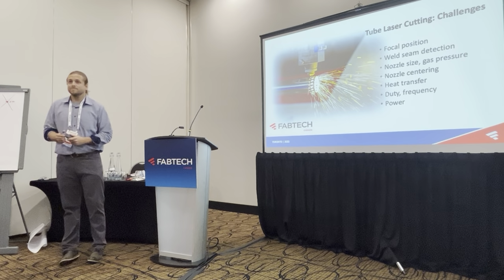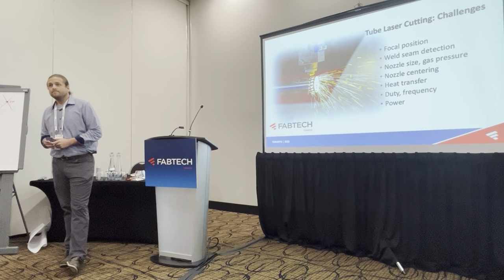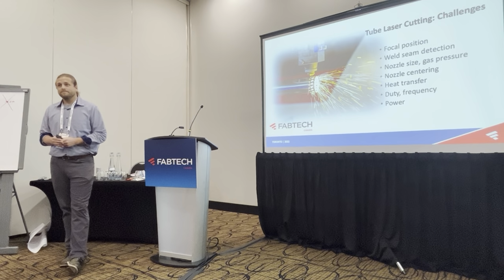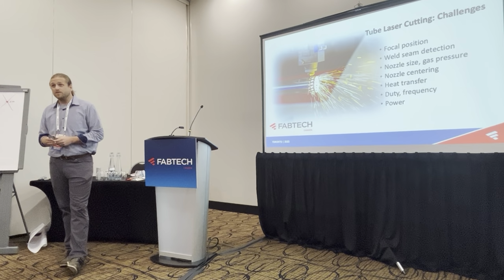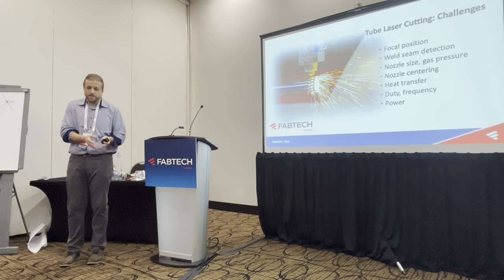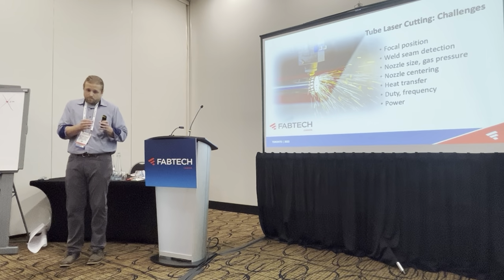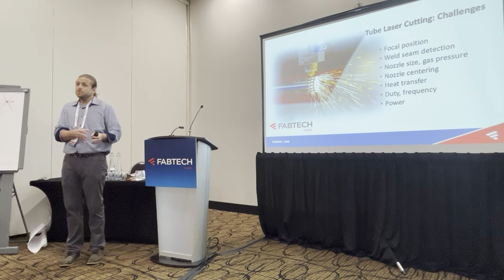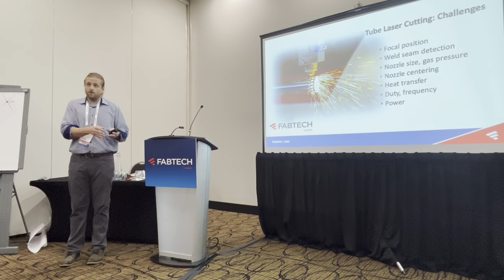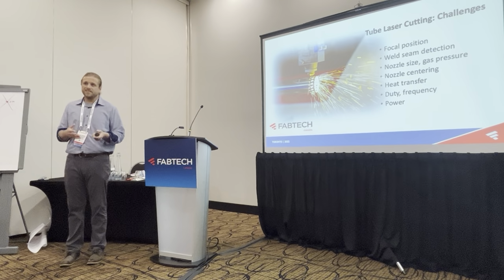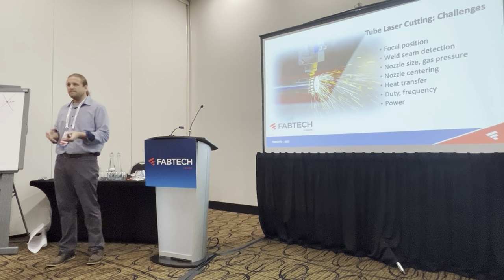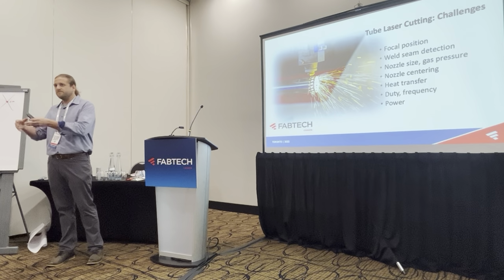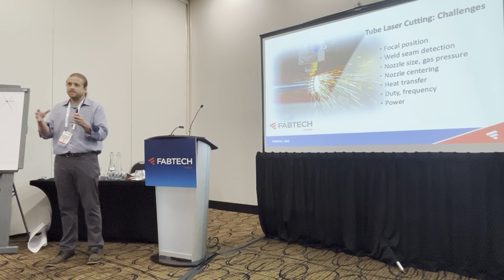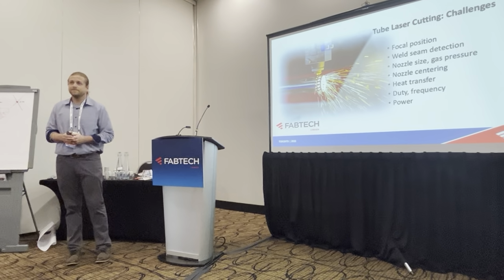So dimensional tolerance, can we maintain that with regards to OD and that sort of thing? Yes. Even with copper? Yes. Yep. And lasers usually can hold, I mean, you can hold down as tight as, I've seen a really dialed in laser, 2.5 with fallout and a full 100% check on a fixture. But standard, you like to say you can hold 5 thousandths on hole size up to that 10 to 15 thousandths. That's kind of the tolerance range on lasers.